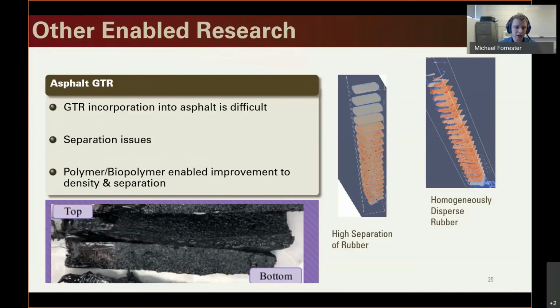And so we did a lot of the screening testing in the Haake system, and we had such good results with that, we started to move up to the larger scale so we could start looking at images like these two. So this would be a typical GTR unmodified system where you get much, much lower GTR content towards the top than the bottom. Whereas once you've incorporated that additional rubber to swell and match densities, you end up getting something that's much more homogeneously dispersed. So this system was really instrumental in getting this project off the ground.